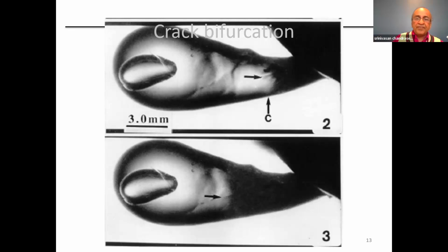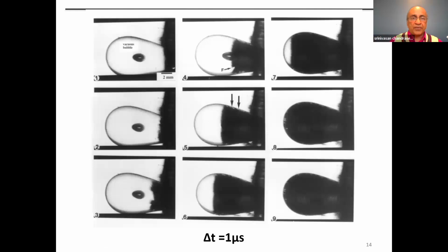This is more of the same, another sequence taken at 1,000,000 frames per second. Here again, if you look at the front, you will see finger-like features. So this is characteristic of every fracture front we observed in these drops. I showed one before, and this is another sequence. Here again, it goes 1, 2, 3, 4, all the way to 9.